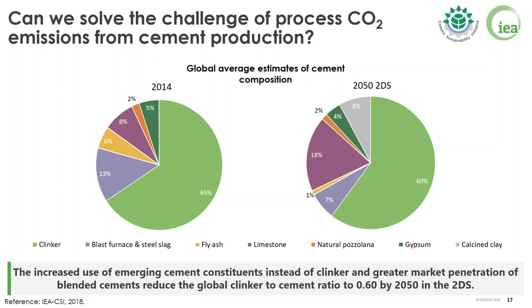This is also one of the reasons for the increase of contribution of limestone to the total composition in 2050. About calcined clay, it needs thermal treatment, and it is in fact the result of drying, crushing, and calcination of clay. And we have seen before this will bring a penalty in terms of energy consumption. The result of this change of composition of cement, we said, will deliver 37% of cumulative savings overall.